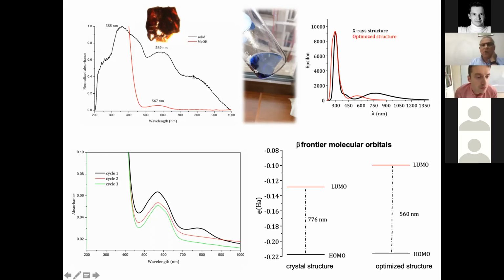In order to identify the origin of this band, we carried out DFT calculations for the molecule like the one we observed in the crystal structure. I mean, the one with the oxygen above the plane of the molecule. And we observed a transition around 800 nanometers, this one here, that disappears by diluting the solution. So these three spectra were recorded at different times. First, in the first step, we observe this. This is the same solution. We observe this band, and in time, this band disappears, but we still have this band here.